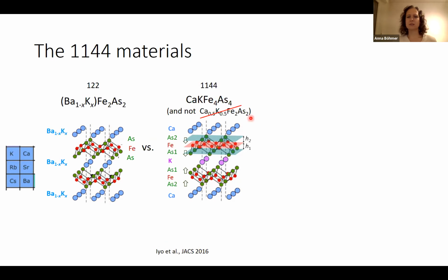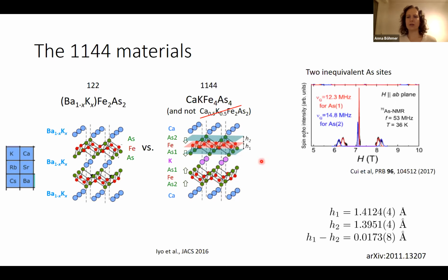And that has consequences on the symmetry. So now we have two distinct arsenic sites, one's close to calcium and one's close to potassium. That can be seen, for example, in the arsenic NMR spectrum. It also is seen in the structure. So we have a very detailed structural refinement, the height of the one arsenic plane and the other ones are distinct from the iron side. So they're shifted out of their symmetric position here.